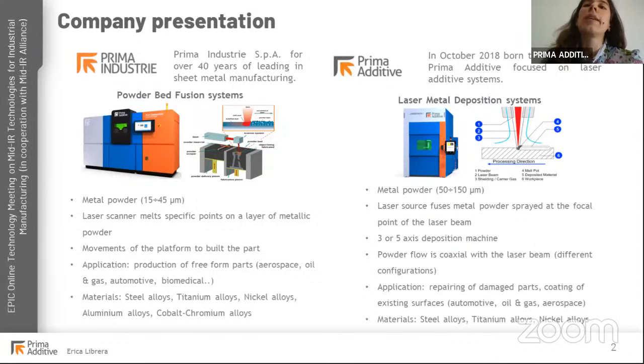With the movement of the laser, we are able to melt some points and areas in order to define a precise geometry. The movement of the platform on which the powder bed is located allows us to generate a three-dimensional part. In the case of a laser metal deposition system, the situation is different because the powder is in motion, sprayed from a nozzle tip with the help of a carrier gas, an inert gas.